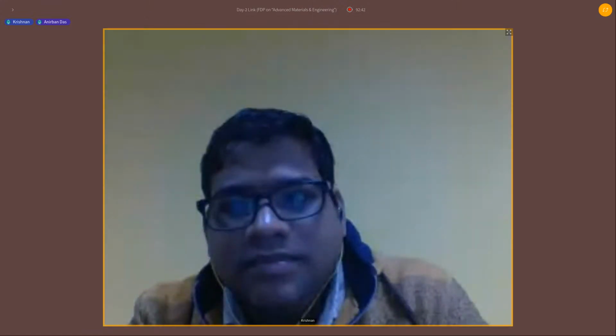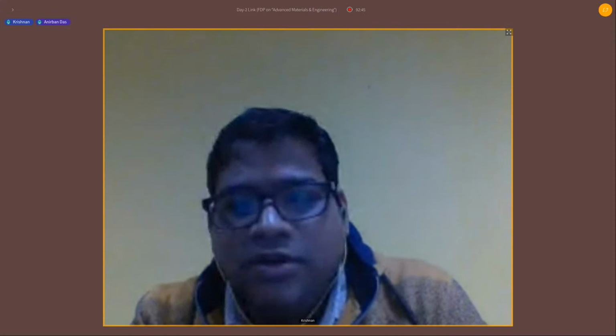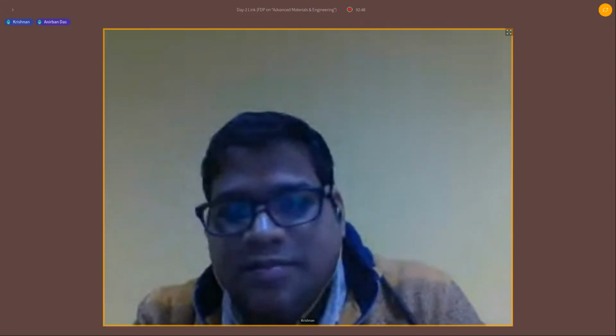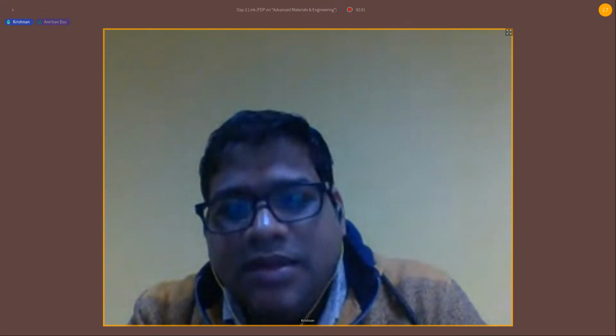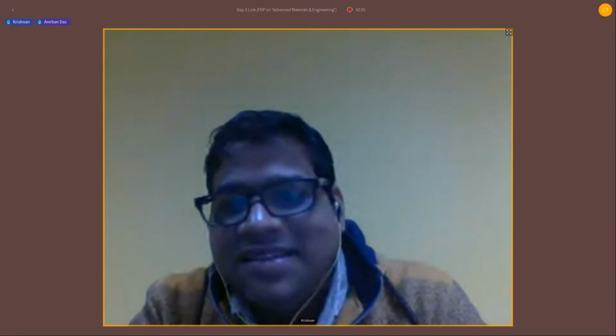No, that is defect free. We designed it as a single crystal material. In a polycrystal material, defects are associated, but we can check it after loading. Maybe localized deformation is taken. From DXA analysis, that is dislocation analysis in OVITO, we can check how much partial and Frank deformation has occurred in this surface. Okay, I'm asking about while designing the sample, have you considered any sort of defects? No, we considered a single crystal, pure and defect free. That's the main reason the property is high. So you are getting better properties. Yes.